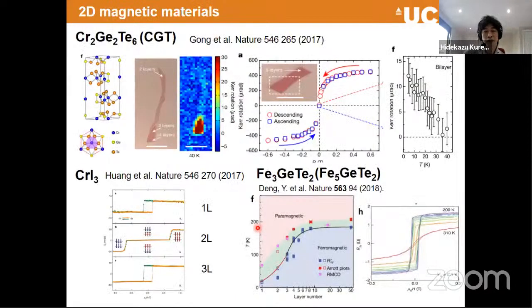Right. So then just to give you some flavor of which kind of materials we can use, I pick the typical or popular materials that we have used since they discovered that we can exfoliate and maintain the magnetism in the few-monolayer regime. These two are insulators, and this is ferromagnetic. This can provide a ferromagnetic order. You can see that we exfoliate it down to a few monolayers and can still maintain some kind of hysteresis, an M-H loop that looks like ferromagnetic order. Also this chromium iodide is antiferromagnetic in the thin film regime, and that can produce layer-dependent magnetism as well.